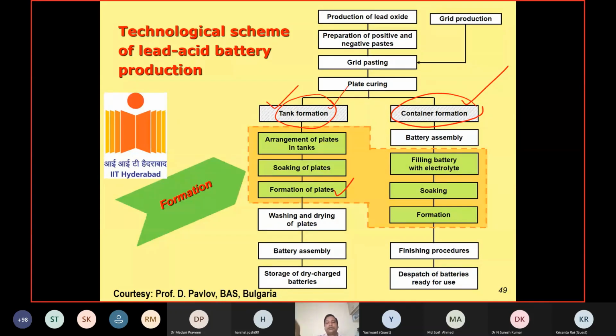So they do charging also in situ. So here electrodes are done in a big tank. Here the stacks, the positive and negative electrodes together, are put into the stack, and the electrolyte is filled, and then soaking, and then formation is done. Here it is separate. So the plates are arranged in a tank and the formation is done. And then when the formation is done, they store it, and whenever it is required, they assemble it, and then again they charge it.